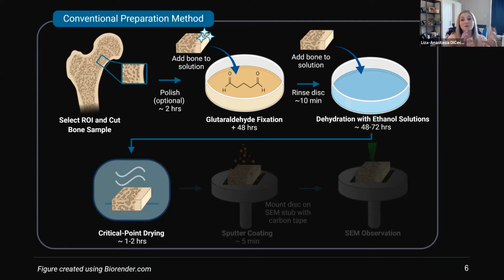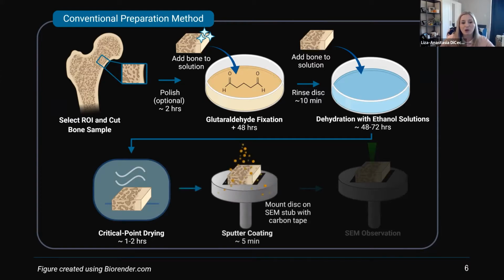And I'm like, well, if you're looking at Jello, which is analogous to a lot of gelatinous kind of biomaterials, you're looking at Jello in its hydrated state versus its dehydrated state. The morphology is completely different. So that's something to keep in mind when you're dealing with these dehydrated samples as well. So again, we have it dehydrated now, but they're not conductive, so we have to do a sputter coating.